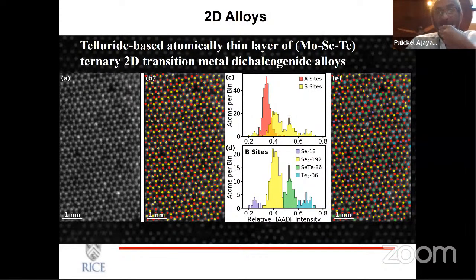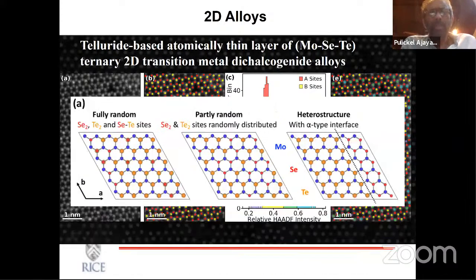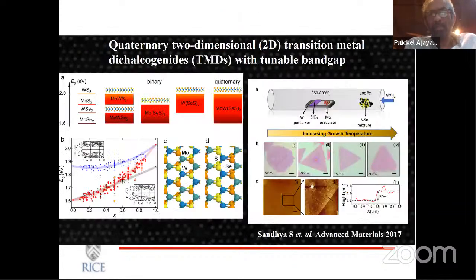In fact, before we actually got a good microscope, a Titan, we were working with Oak Ridge National Lab, and a lot of the images that you're seeing here are actually from Oak Ridge, the energy filtered imaging. So if you have a multi-component system, three-component or more, at the end of the day, you can get either a totally random distribution or partly random or even completely segregated heterostructure. If you look at the selenium and the tellurium sites, and again, this has been seen.